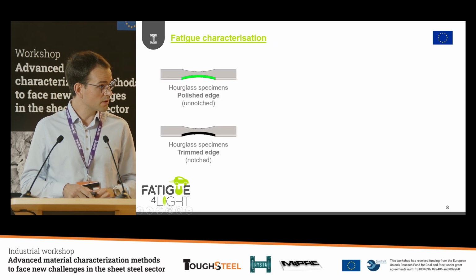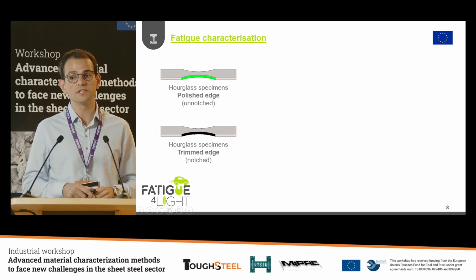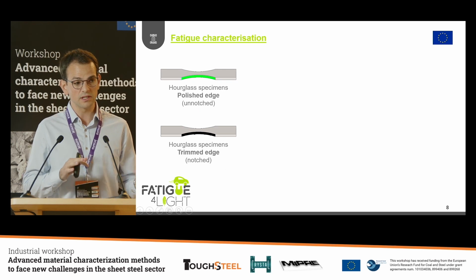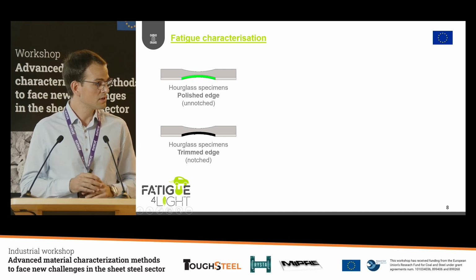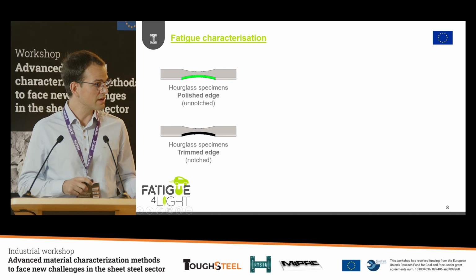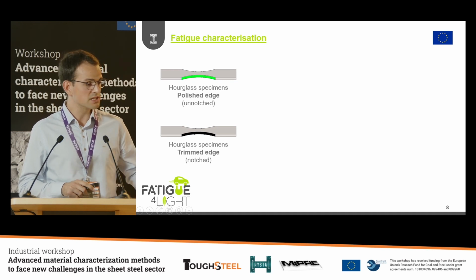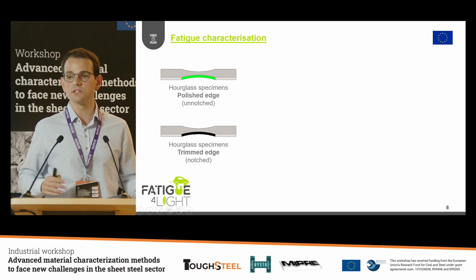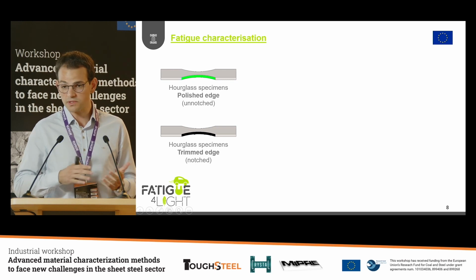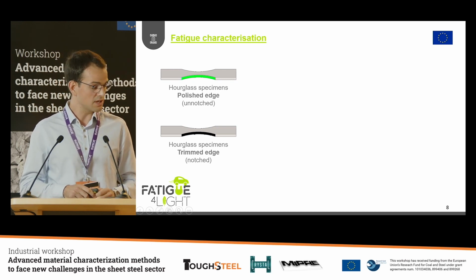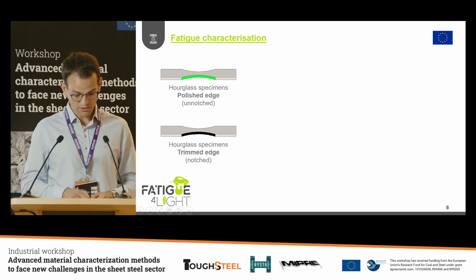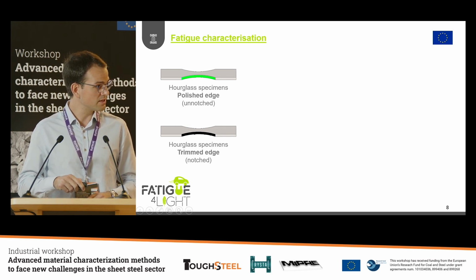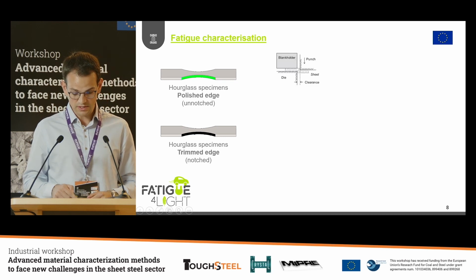In this case, we evaluated the fatigue resistance of the material by testing two different conditions. On one side, we have these hourglass specimens with a polished surface. So this is the perfect condition, let's say, without defects, and can be considered unnotched specimens. And on the other side, we have these trimmed specimens, where we have the defect here in the edge, and we can consider them as notched.